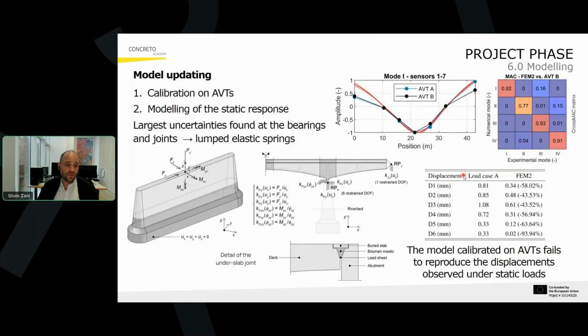Something very important was the model updating. This was the final phase of this research, in which we were able to calibrate a numerical model on ambient vibration tests. Here you see the comparison between one mode shape on one side of the bridge. The comparison is between the red curve, which is the numerical one, and the black and light blue ones, which are associated with the experimental measurements, and also the cross MAC matrix, which highlights how the numerical model gets closer to the real measurements.